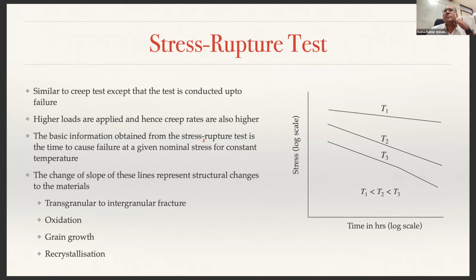The information that we obtain from this test is the time to cause failure at a given nominal stress for a constant temperature. You maintain at temperature T1, and if you are applying a particular constant stress, this is the time that it takes at T1 for failure at that particular stress value. So you are operating at constant stress and checking what is the time taken for failure at a given temperature. You can see at different temperatures the slope is changing, and within a given temperature also there may be a change of slopes. T1 is the highest temperature, followed by T2 and T3.